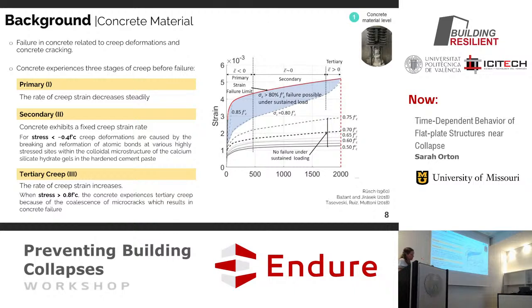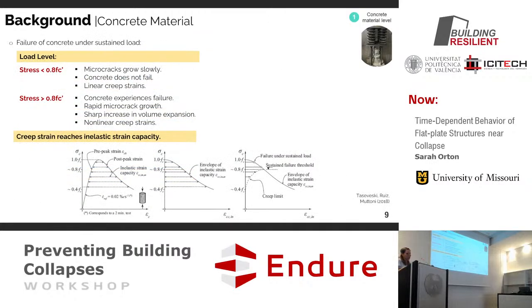A lot of this research was done very early by Rüsch. And then our colleague here, Manuel, did some very nice work with his group recently, which we took and realized it worked very nicely. So I didn't have to reconstruct anything. Less than about 80%, maybe 70%, the cracks are growing slowly. Concrete does not fail. You have essentially linear creep strains. If you get to the higher one, then you can have rapid microcrack growth and a sharp increase in volume expansion, nonlinear strains. And one of the things that Manuel Ruiz and his group did is this idea of inelastic